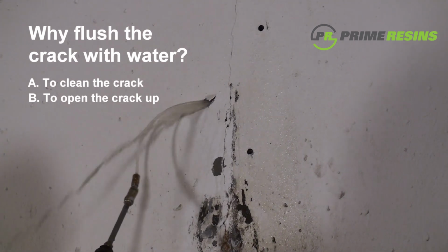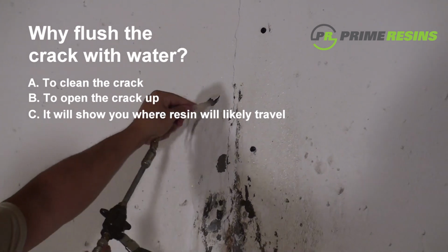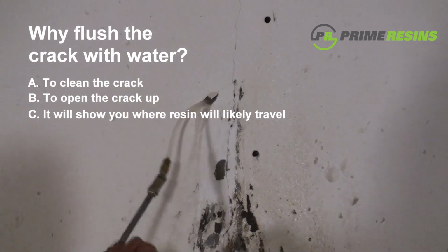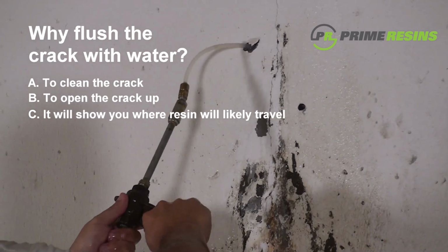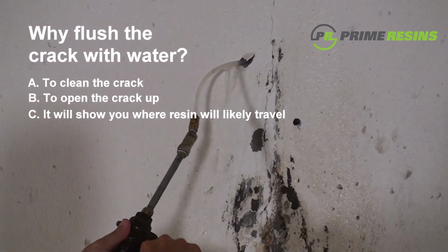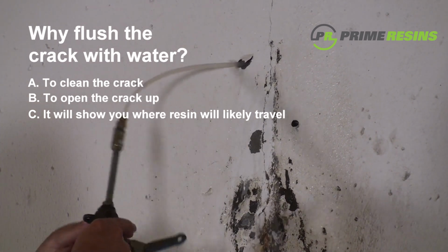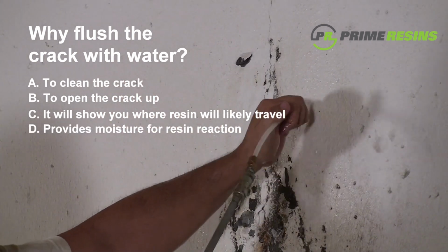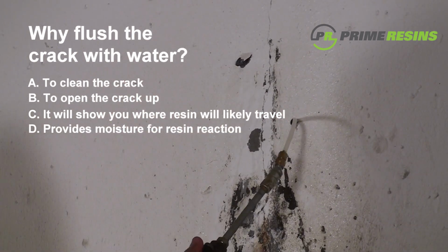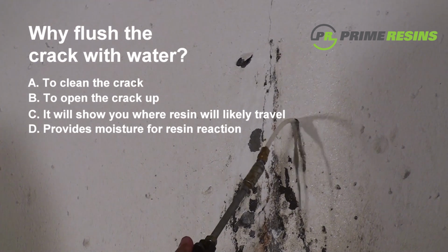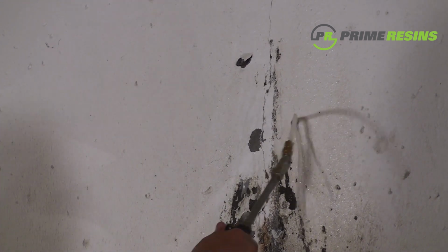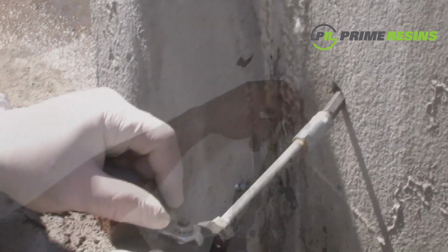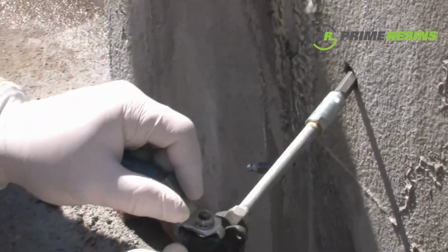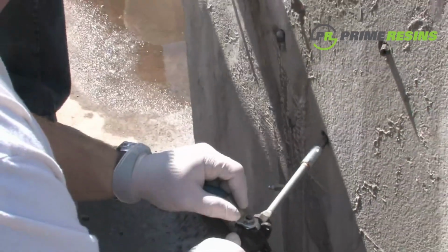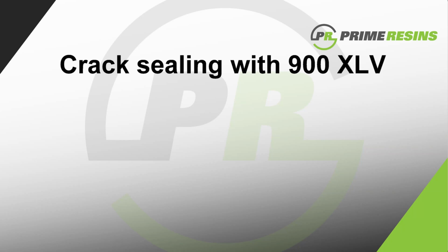C. Injecting the water shows you where the resin is probably going to travel. As you inject water into the crack, it will show up at the face of the concrete, giving you a good indication as to how far the resin will travel. And finally, D. Injecting water into the crack ensures that there isn't drilling debris in the port and that the resin will have enough moisture to react. Now that the crack is clean and full of water, you're ready for step five, and that's to inject the PrimeFlex 900 XLV.